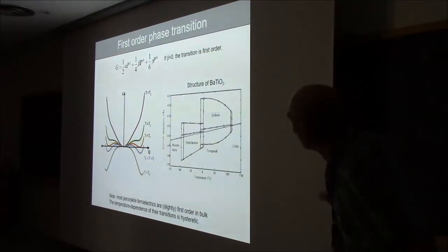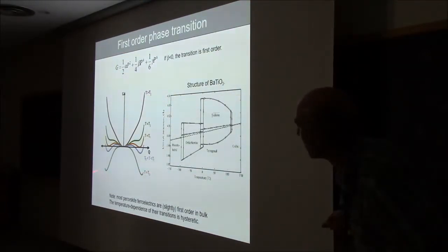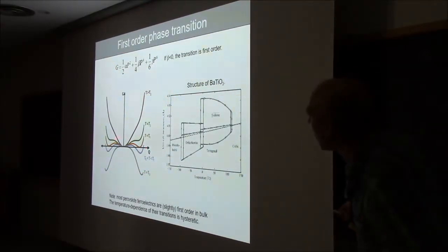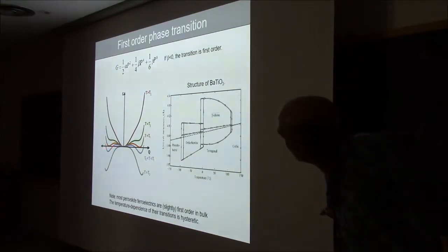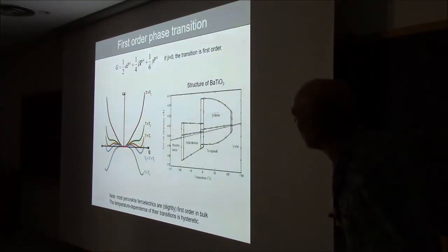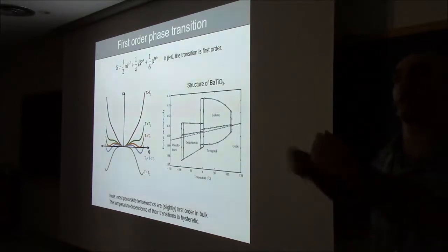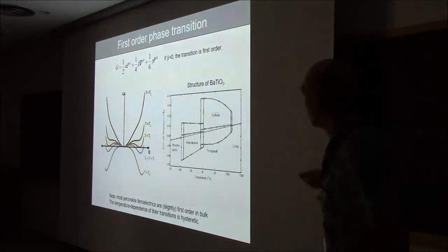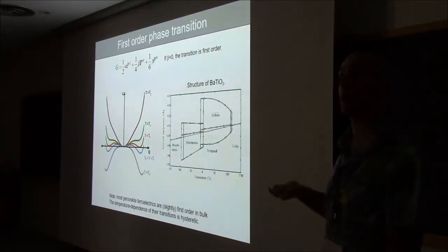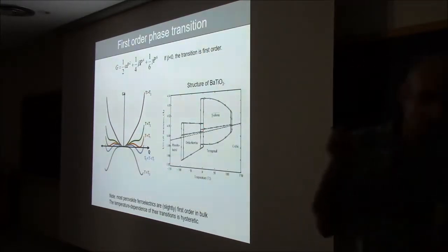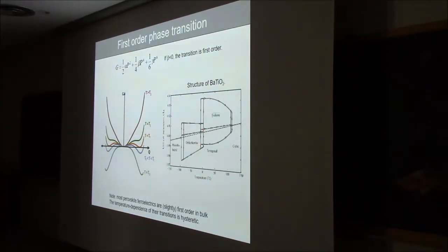When these two are very strongly negative, you are definitely in the polar phase. And in between, you can have a metastable polar phase, or you can have a metastable non-polar phase, depending on where you are cooling or heating. And that's why in first order phase transitions, you have some hysteresis. So when you measure the polarization of the structure as a function of temperature in a ferroelectric, if you see hysteresis, it's an indication that the phase transition really is first order.